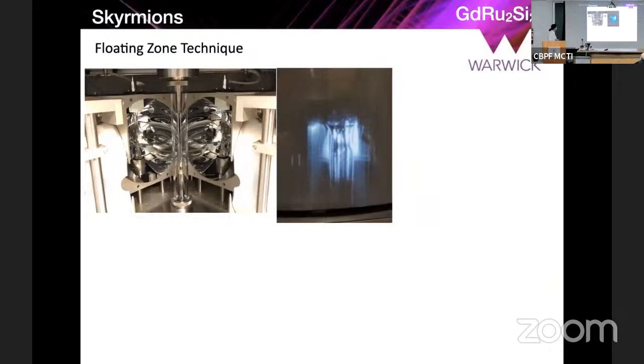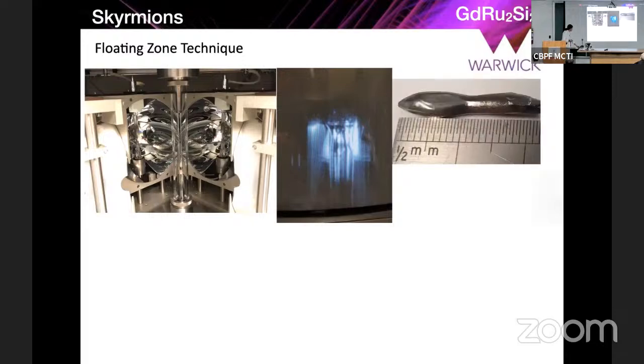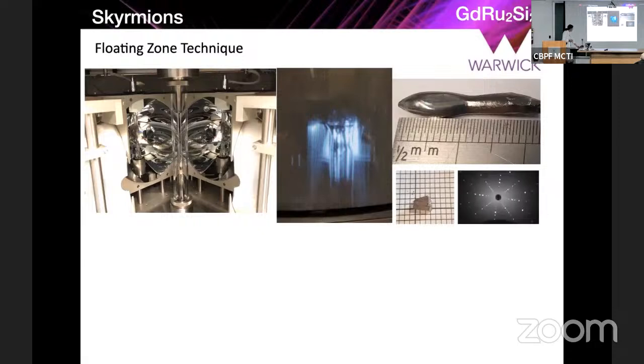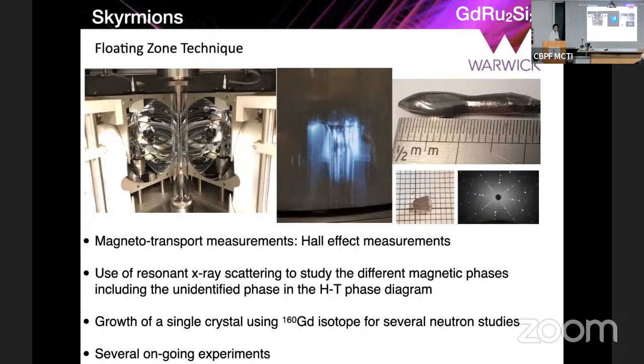So once again here, we've been able to grow large single crystals using the floating zone technique. And you can isolate crystals that are big enough for your measurements. And this forms the PhD project of one of my students, George Wood. And he's conducting a lot of measurements using X-ray scattering as well as neutron diffraction. You might wonder how neutron diffraction is possible with the gadolinium nuclei because gadolinium is very highly absorbing for neutrons. So what we have done is that we've robbed the bank to buy about 1 gram of this isotope here, 160 gadolinium isotope, which cost us about $12,500.